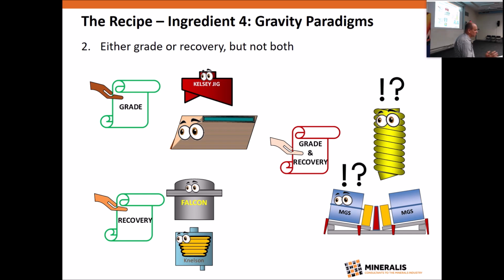We already talked about grain planning, but I spent quite some time at Hill End, which is north of Bathurst in New South Wales. We're close to where gold was first discovered in Australia, and all the gold there was in plus half millimetre particles. It was huge, and yet we still couldn't achieve grade and recovery in one gravity step. So it's not a very common situation.